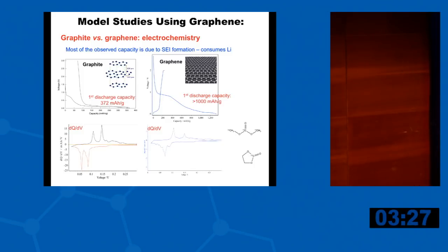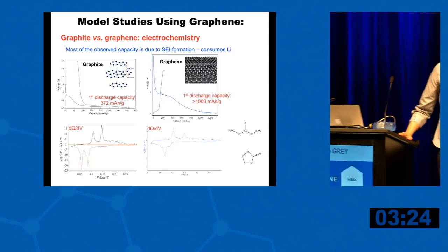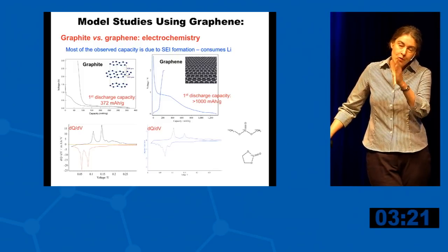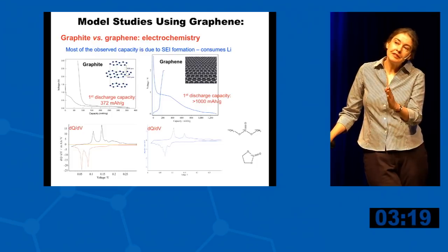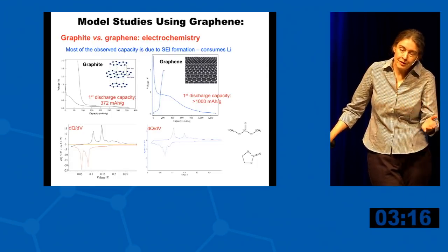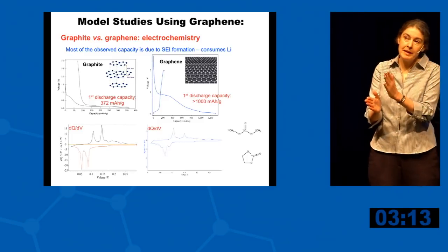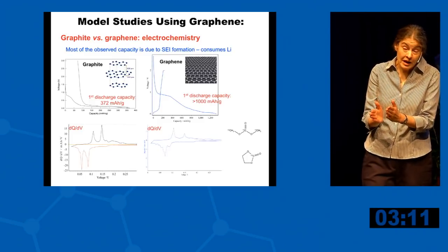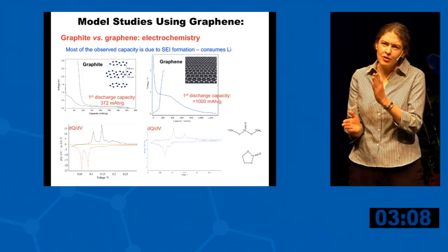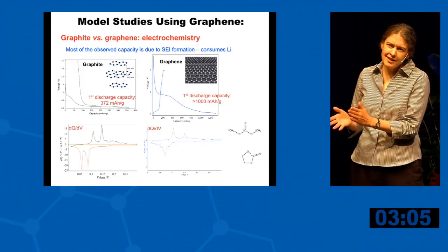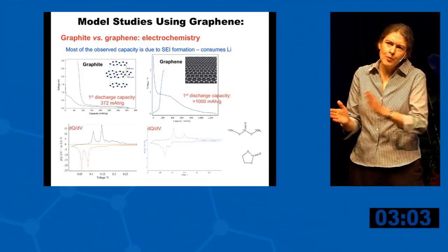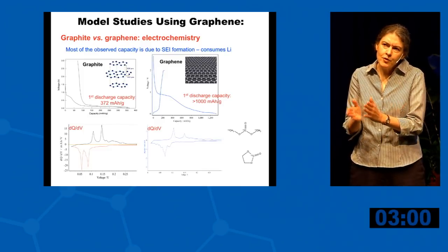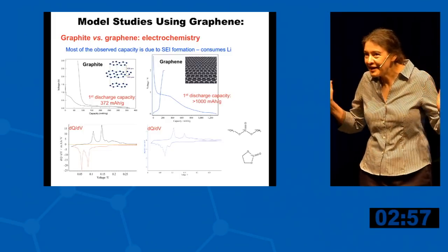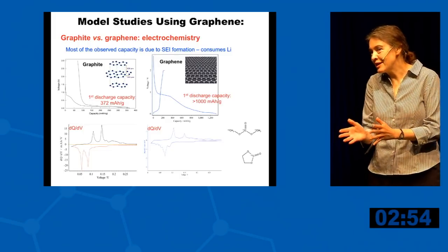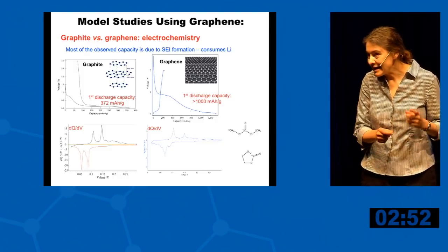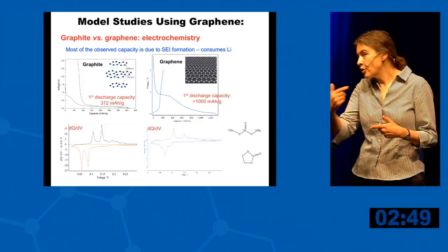Well, that was sort of another reason we were doing that, is that you can then tolerate some water. The problem you have, of course, is the lithium metal. We've been very successful in getting multiple cycles because you form a hydroxide on the lithium metal that passivates it to a degree, but is that enough for it to be commercial? The field is moving to protecting the lithium metal with ceramic, which will also help you against the nitrogen problem. So if you can get the lithium metal solved, the big if, which will be useful for so many other fields, then you could probably deal with more water. But I think you're still going to have to control the water.